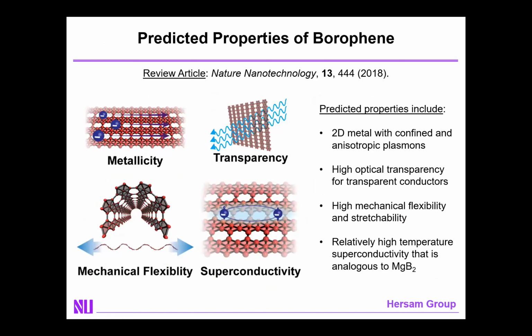And if you were able to realize such a structure, there are many properties that have been predicted. This should be a 2D metal with confined and anisotropic plasmons. It should have high optical transparency and therefore be useful for transparent conductors. It should have high mechanical flexibility and stretchability. And since boron is one of the lightest elements in the periodic table, it's predicted to have relatively high temperature superconductivity, analogous to magnesium diboride. And as a result, these sets of properties are of interest and therefore help motivate the realization of boron in the 2D limit.